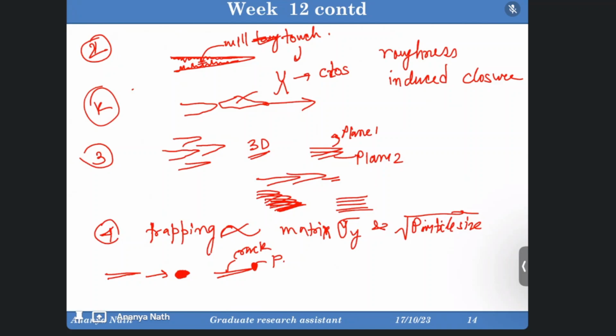And the next thing is that the matrix yield strength will also differ the crack trapping. Then also, one thing, it's not like particle size, okay, I'll decrease the particle size and the crack trapping will always increase. It's not like that. It's like up to a certain point, the particle size will trap the crack. But if the particles are 1 nanometer, 2 nanometer diameter, if it's spherical, then it cannot trap the crack. The crack will overcome the barrier of the particle and it will just propagate.